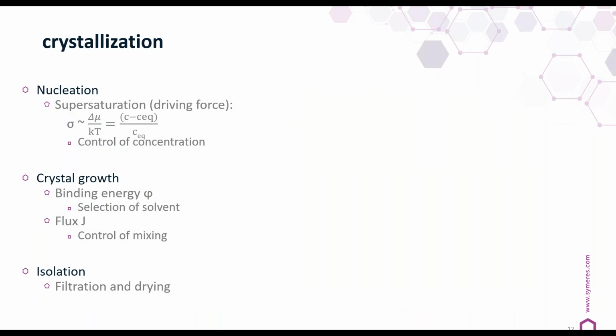So crystallization. Of course, you can measure a lot and you can put a lot of theory behind it, but the idea is, if you want to control something about your nucleation, it is driven by supersaturation. That is the reason why it starts to nucleate. And that is actually controlled by your concentration, actually your concentration difference. So what is your actual concentration compared to the equilibrium concentration at that condition? If you steer that one, if you have a higher supersaturation, it will nucleate in a different way or faster.